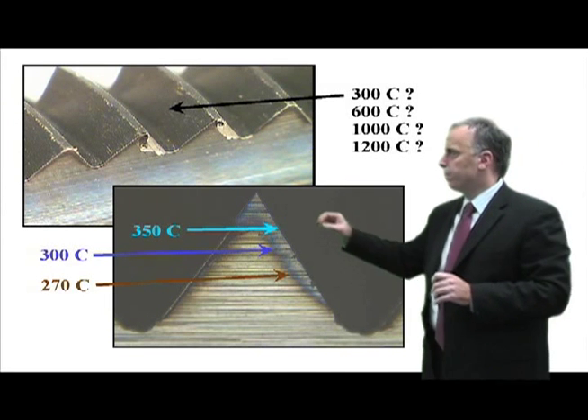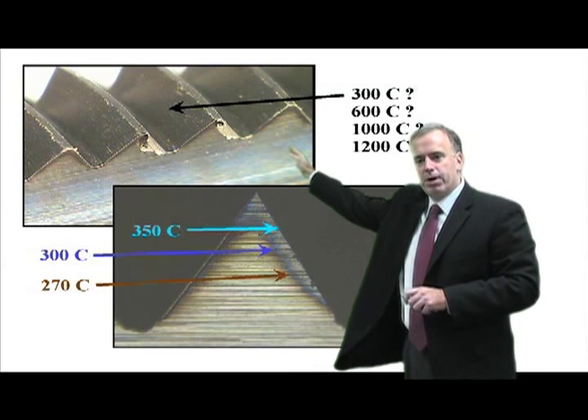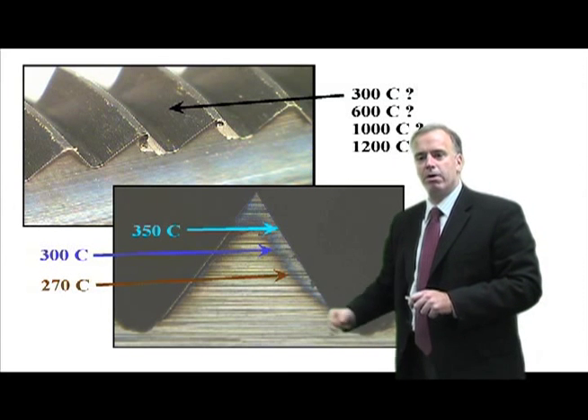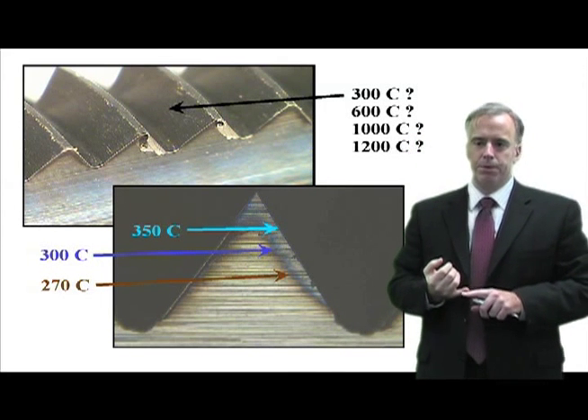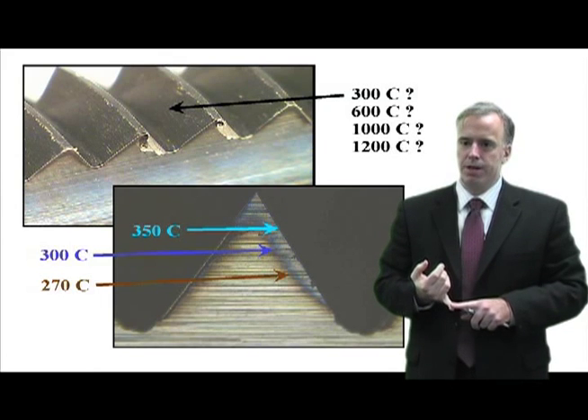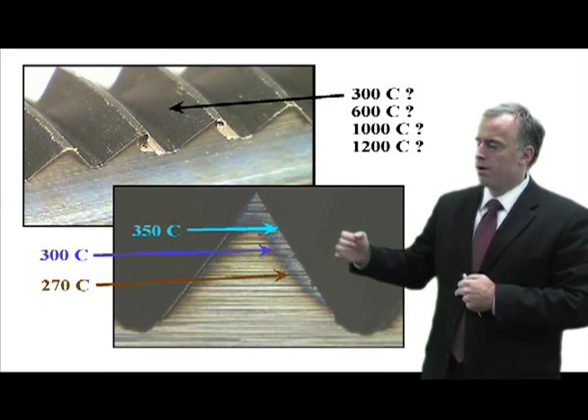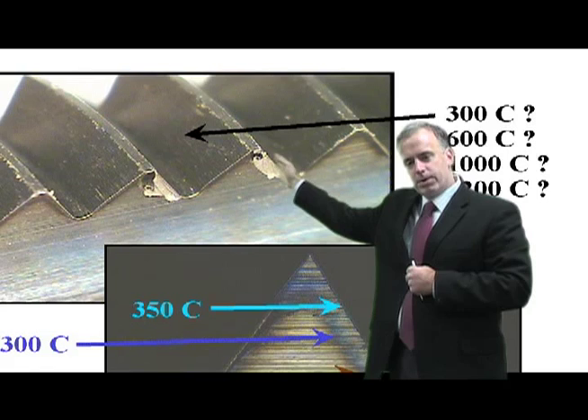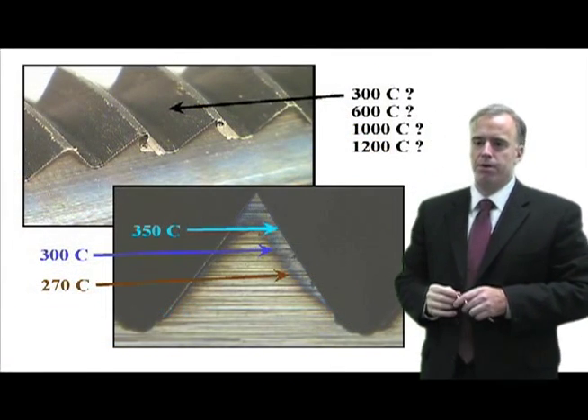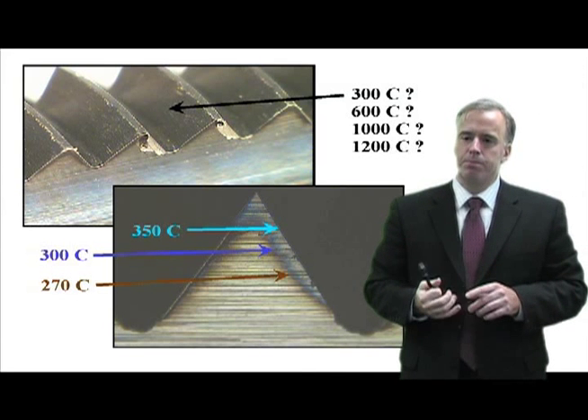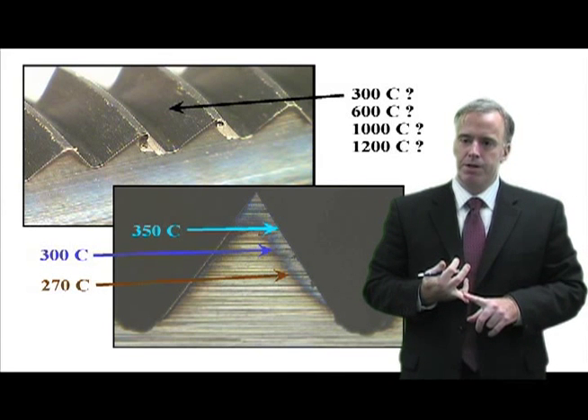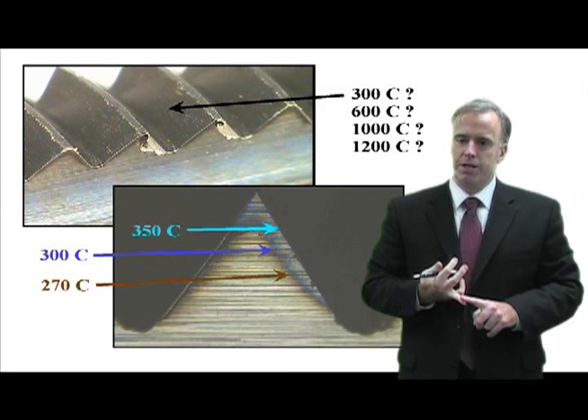So it's conceivable that in the thread grinding operation, the temperature got above 1100°C. We have genuine thermal damage, and we can't see it because it's invisible. The temperature on the unground surface only reached maybe 300°C. That's below the region of genuine thermal damage, but we see the oxidation burn - the brown, yellow, and blue marks.